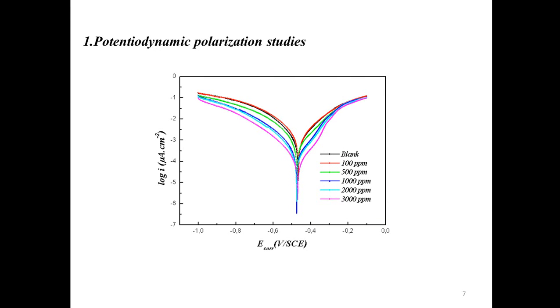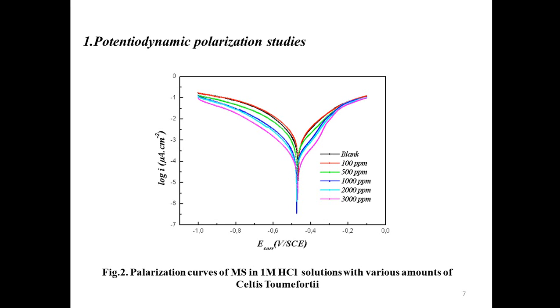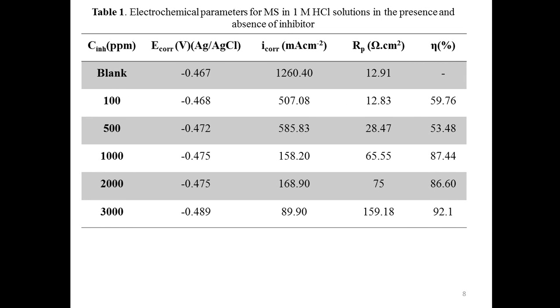The potentiodynamic polarization plots for mild steel in 1 molar HCl solution without and with addition of various concentrations of Celtis tournefortii are shown in figure 1. The different electrochemical parameters determined from the polarization curves are listed in table 1. According to the data provided in table 1, corrosion current density decreases in the presence of inhibitor due to the blocking of the active sites of the mild steel. Increasing inhibitor concentration reduces current density. The inhibition efficiency increases with increasing inhibitor concentration and reaches 92% at 3000 ppm of the inhibitor.